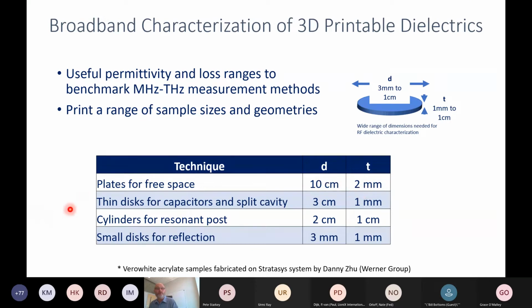But then for capacitors or split cavity, we probably need something a little thinner to get into the impedance ranges that we need. And then for split post or resonant post, we need, well, for resonant post, we need something that's a very tall cylinder, for example. And then for some of the coaxial line ones, we have very small samples. So I think 3D printable dielectrics just provides a way to have a common material that we can make into a variety of different geometries to then compare all these different measurement techniques.